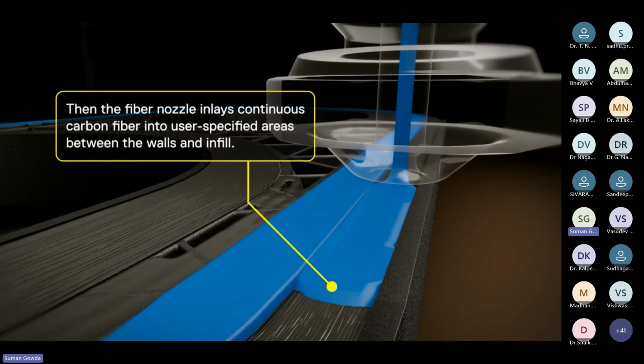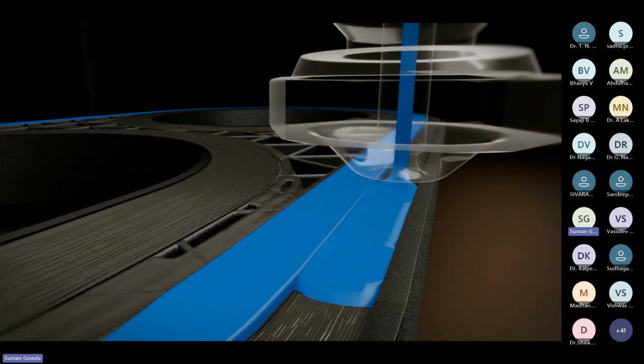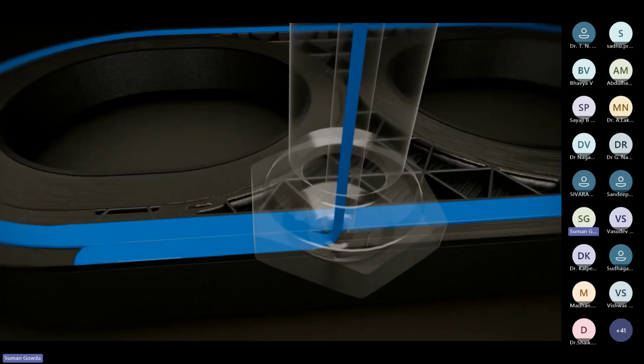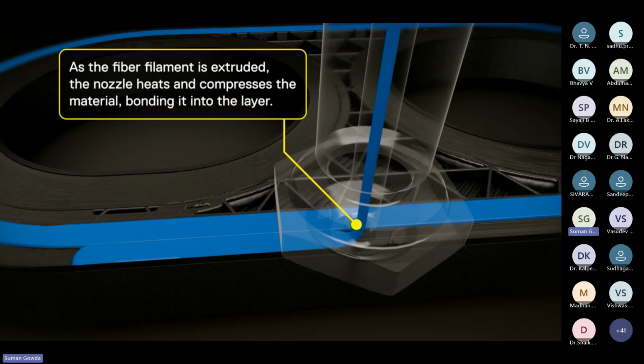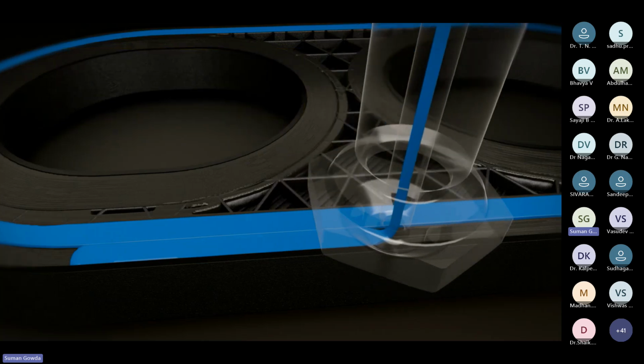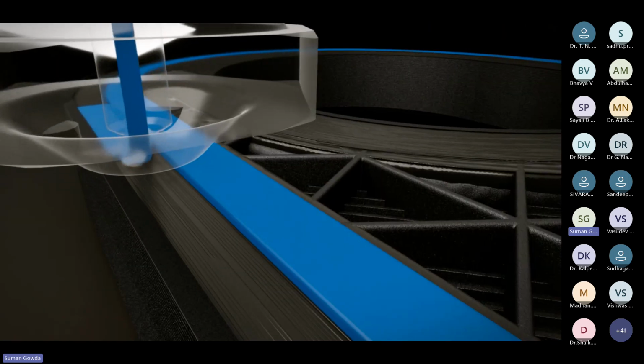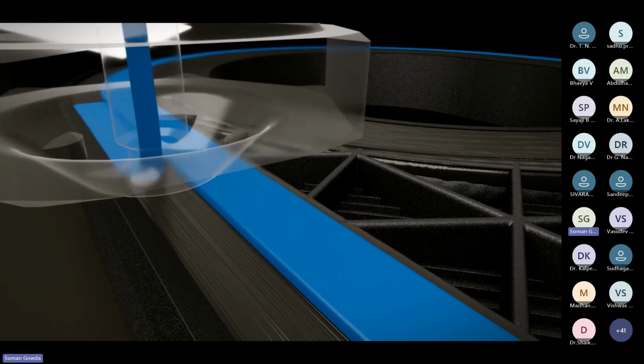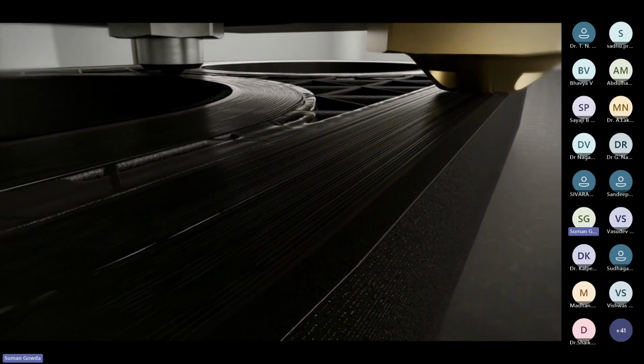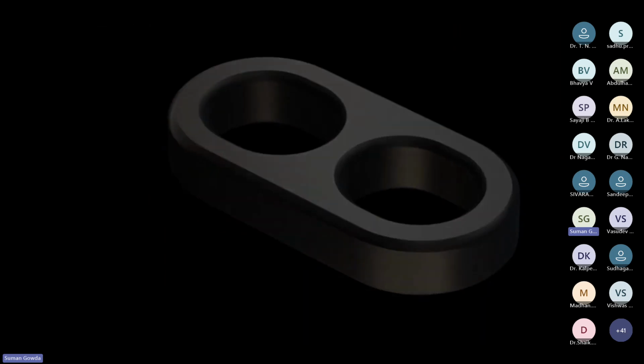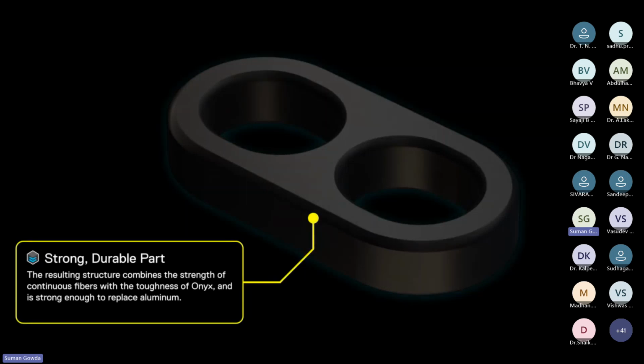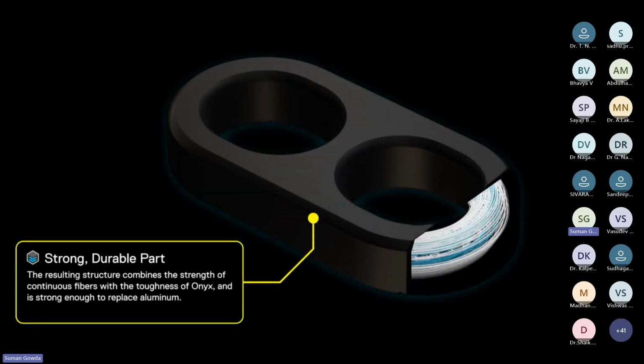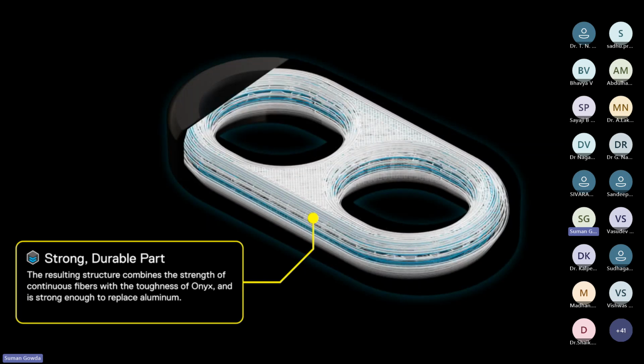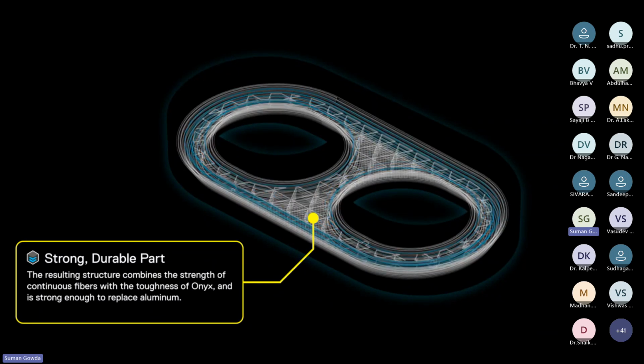This press, everything is pre-calculated from the software. We also have a small cutter which cuts the fiber just before the end spot, so that the fiber doesn't get stretched along once the printing is completed of that particular layer. So this is just to showcase the material when the printing is happening. If you look into the kind of an X-ray version view, the white material is actually the regular plastics, whereas the blue is the fiber material.